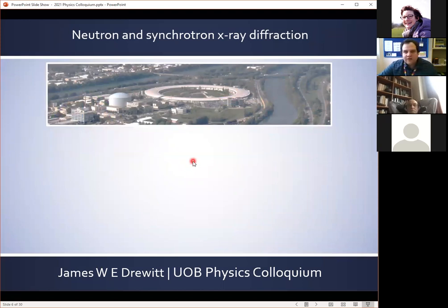Okay, so once we've generated these extreme conditions, we have our melt at high temperature or high pressure. It's necessary to measure the melt structure. And for this, we need to know the bulk structure, so we need a deeply penetrating probe. So we use high energy X-rays from synchrotron X-ray diffraction or neutron diffraction techniques.